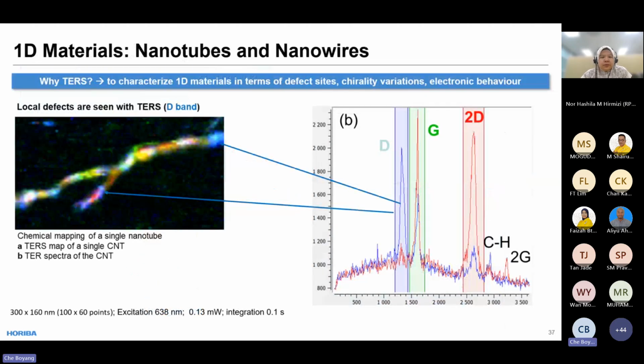So this is an example to show this kind of capability. If you are using the nano Raman, we are able to scan very small size samples. For example, this is a carbon nanotube. We'll scan AFM first to get the morphology of this tube. So this is a single tube, and then we can do the Raman mapping. And the mapping will be exactly the same resolution as the AFM. So we are able to get the nanometer resolution here. In this case, we're studying the D and G bands, so we can get a little bit of information about the defect of your carbon nanotube along this single tube here.